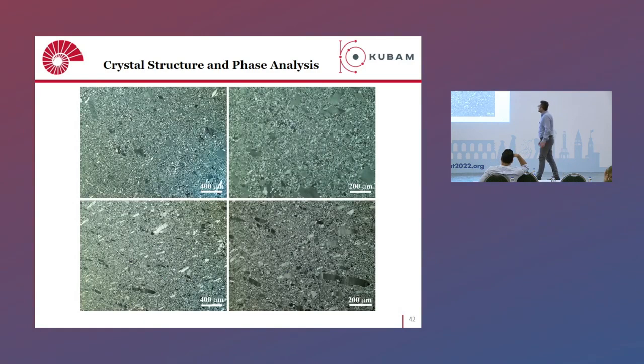So these are the optical images. These two are the cross-plane direction, and this is the in-plane direction. There is a striking difference between them. In the in-plane direction, we see very nice layers of bismuth antimony telluride, which means the main orientation is towards the in-plane direction. This is perpendicular to the SPS direction. This is also nice because it can improve the electronic transport through the in-plane direction.